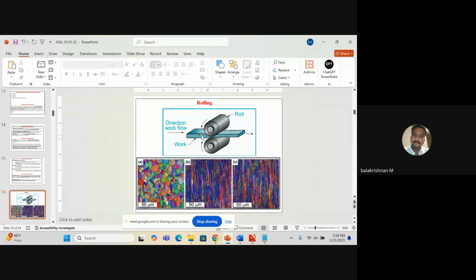In this process, we can observe three EBSD images where the grain orientation is totally different, because in this process the compressive force acts as a refining factor. That is the forging force due to the rolling direction, and the thickness of the composite will differ.